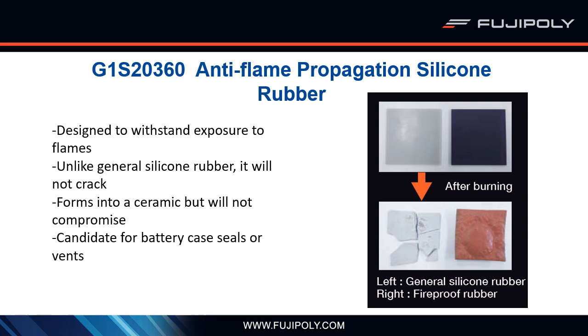When you look at the material on the right, this is actually our G1S20360. This material is actually going to solidify. So it's going to go from an elastomer to a very hard, almost like a hard ceramic material. But the important thing is that it's not going to break. So it's going to maintain its integrity and keep flames from coming in or out. And hopefully, depending on the design, will actually keep air from coming in and out as well. So you're not going to have a situation where you're actually feeding the flame inside the enclosure.